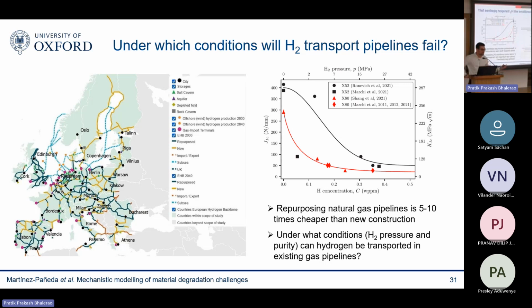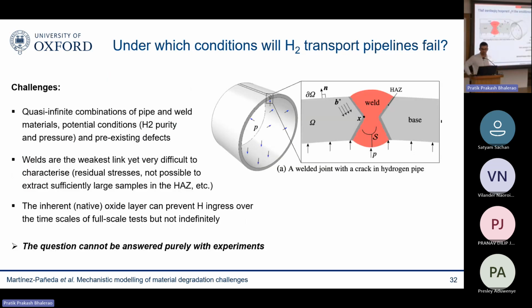What is the hydrogen purity? What is the hydrogen pressure? And this is a very difficult question to answer, particularly with experiments, because first of all, we have an almost quasi-infinite combination of pipelines and weld materials. So these natural gas pipelines have been there for 50 years. They were installed using different materials, using different techniques. They were welded in various different ways. They also have a lot of defects, different defects. Some of them are corroded. Some of them have defects from the welding process.